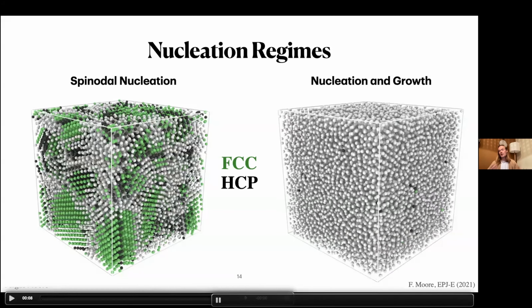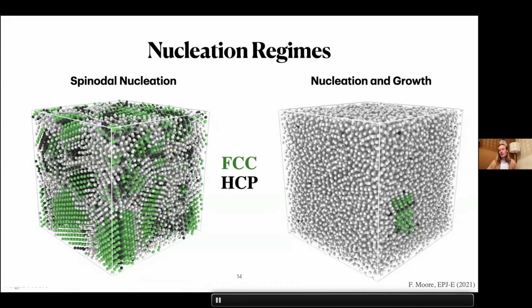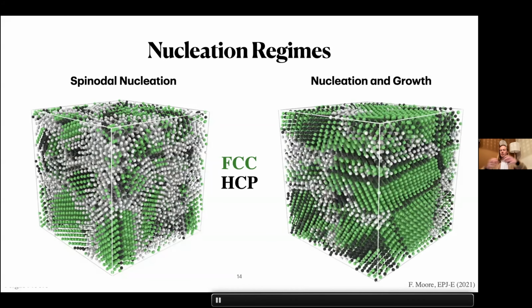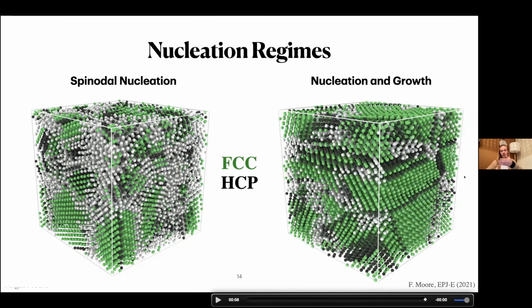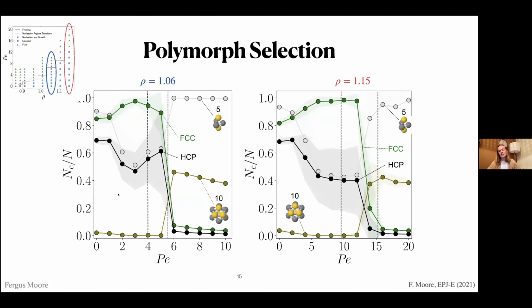Whereas nucleation and growth, nucleation is a rare event. Eventually a nucleus will crystallize and then grow out from a single nucleus. So I trimmed this video. It takes a long time sometimes for that to happen. What happens because of the differences here and the different kind of grain boundaries is, in the spinodal case, which is the lower activity regions, there's a lot more annealing of these HCP boundaries. But when you get to this nucleation and growth regime, then you have slightly less of this, and it trends a bit more towards the passive case of less preference for either polymorph.